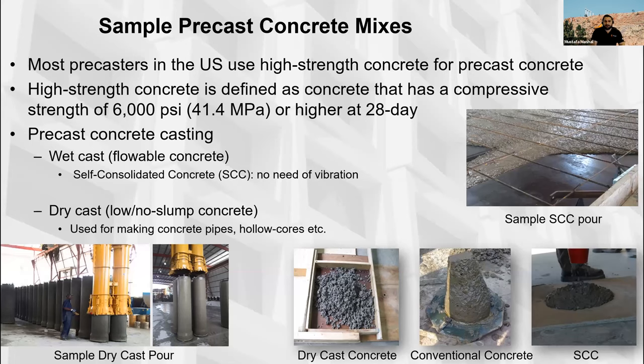Wet cast is flowable concrete. And the majority of precasters use self-consolidating concrete, SCC, where there's no need for vibration because it has plasticizer. If you see the sample SCC pour, as soon as you pour the concrete, it is so runny and it just goes everywhere and fills the voids in the form, and there's no need for vibration at all, unless there are some controlled spots where you want to make sure that there are no voids left.